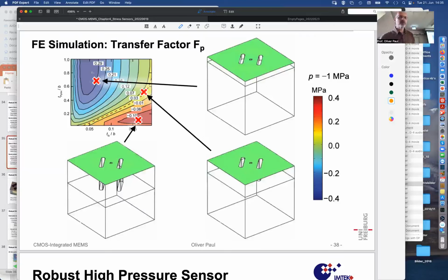And so that gives you a response of a certain strength that is indicated here on this diagram, which is some sensitivity factor. And if you make the component really thick, the silicon component here is rather thick, glass is thinner, then the glass will compress, the silicon will compress less, but then the silicon is forced into a bending. So it's the bottom of the silicon that is pulled towards the center, and the top has no such force. So what happens if you have a body of rubber and you compress it at the bottom?